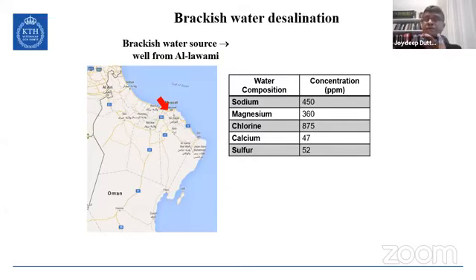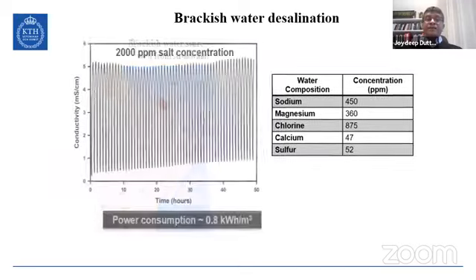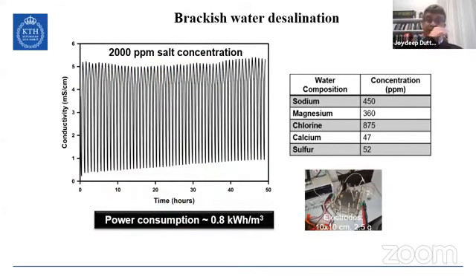Without going into more details of the electrode engineering, which I will touch on later, let me give you an example of some brackish water desalination that we carried out in Oman. This was from Al-Lawami, and we had a concentration of about 2,000 ppm salt. So we could get a pretty uniform removal of salt with a power consumption of less than 1 kilowatt hour.